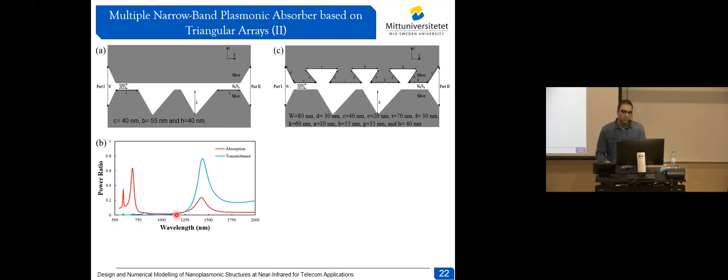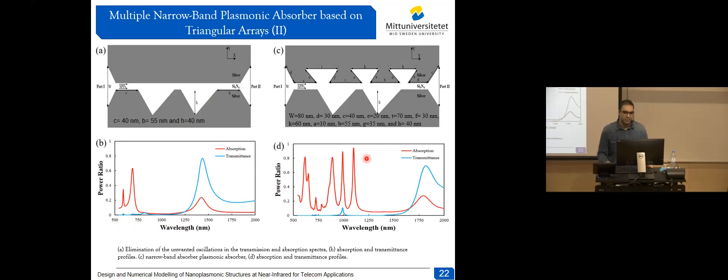The last step is to incorporate the previous designs into the final design structure. In this figure, we create four absorption resonances at visible and near infrared. We have nearly zero transmittance from visible to near infrared with absorption efficiency of more than 81%. By tuning the coupling distance between the adjacent input and the first triangle, we are able to further enhance absorption to 99.3%.